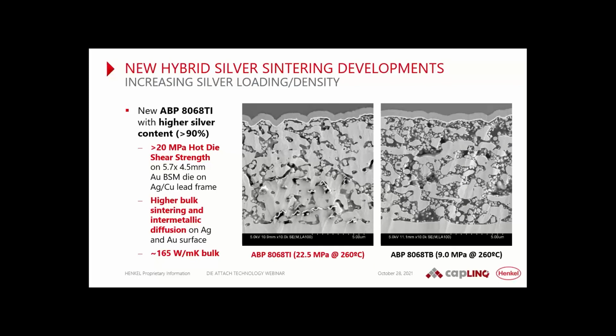And I think there were two approaches we went over. One was going higher silver loading, higher density, as you can see here. That is the TI development. You see also the strength going up. And basically this was to prevent the fracture. So this was one approach.